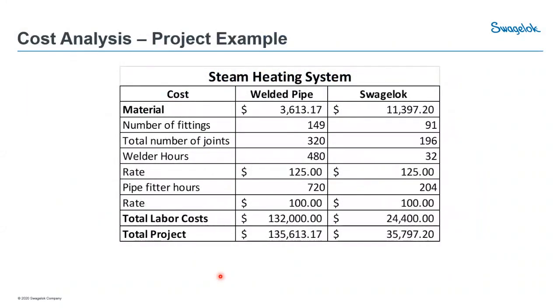Now, let's go through some cost analysis here and give a project example. Now, what you've seen here was actually put together by a contractor. They were looking at a steam heating system, 1 inch in this case, and they wanted to compare welded piping versus a Swagelok tubing system. Now, you'll notice material costs is a little bit less on the piping, $3,600 in this example versus around $11,000 for the Swagelok. But if you look at the number of fittings here, you're looking at approximately 150 fittings versus about 90, but the number of joints, over 300 joints versus about 200, and especially on this welded steam heating system, you're almost at 500 welder hours.